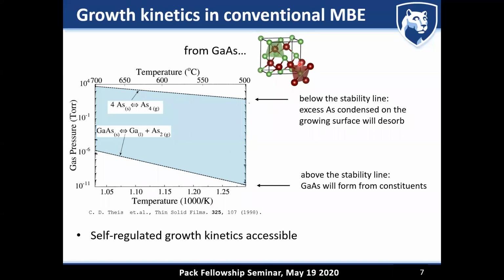So the idea is relatively simple. You can see here the conventional unit cell of gallium arsenide, and you can see it consists of gallium and arsenic. So literally all you have to do is supply gallium and arsenic, and typically you do this through thermal evaporation from an effusion cell. And the only thing that you have to do as you're growing those films is make sure that you're hitting this particular thermodynamic condition. What I'm showing you here is the gas pressure in the system, and that is a measure of the amount of flux of arsenic that you're supplying. And you're seeing here two stability lines. If you keep your arsenic flux above this stability line, then you're going to ensure that gallium arsenide is going to form.